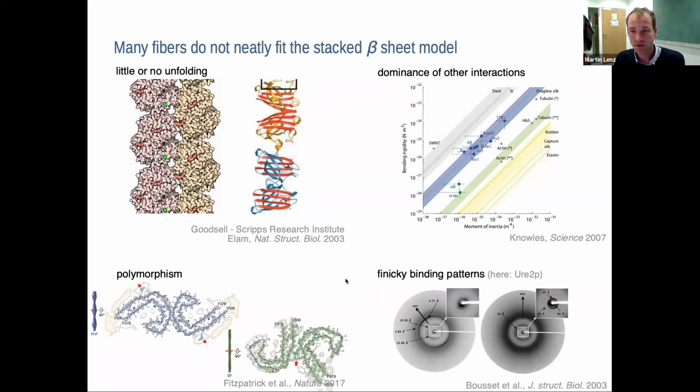And then there's other protein fibers that actually display the hallmarks of amyloid aggregation, such as this 4.7 angstrom ring in some conditions, but then at other temperatures, and actually for this yeast prion, this one is the more physiological temperature, they just aggregate in a completely different manner. So again, this is a complicated question, and there's not a single protein fiber structure, even for a given protein.